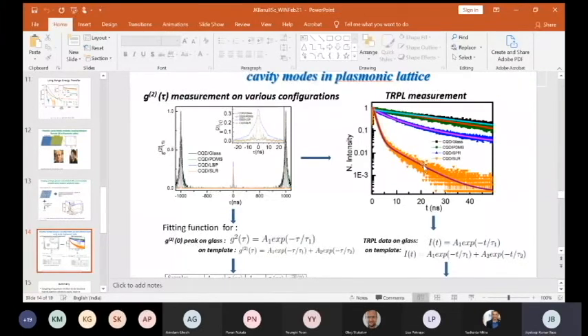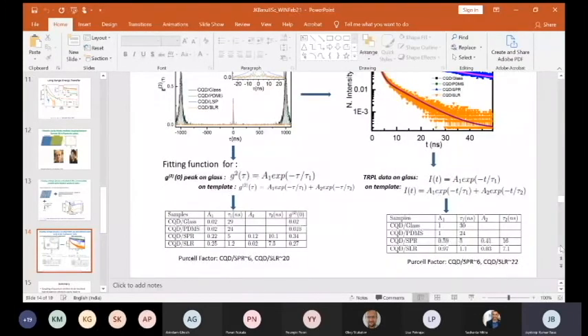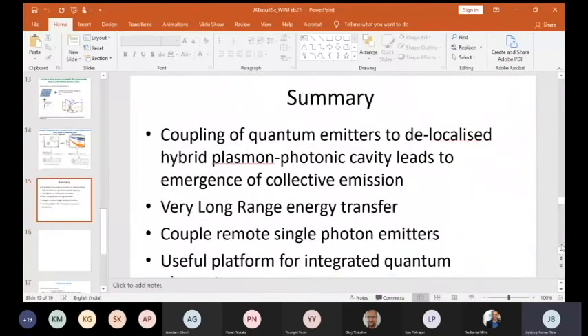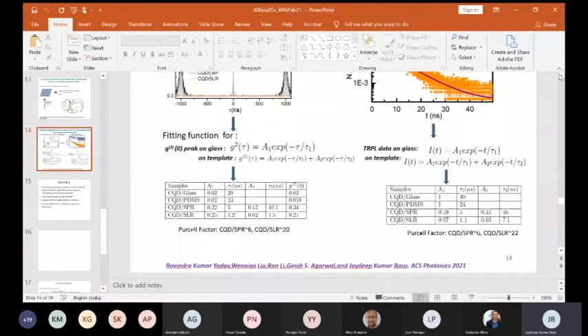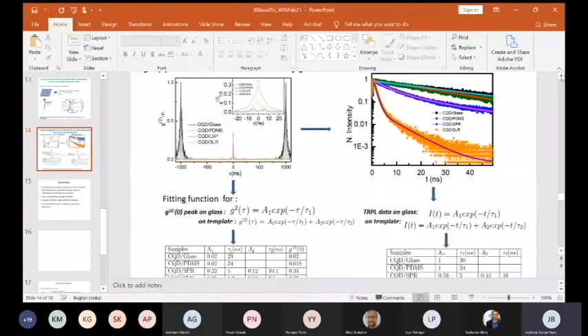And if you look at this one here in particular, you see a very strong signature, both in terms of enhancement of the decay rate, but also the emergence of a second contribution. I don't have time to explain in detail, but we modeled this with the help of the group of Girish Agarwal at Texas A&M. If you do a detailed quantum mechanical model, because this is not captured by classical models, you use a full quantum model using the entire Hamiltonian picture. Essentially, what emerges is a possibility of lattice-mediated excitation of a nearby quantum dot.